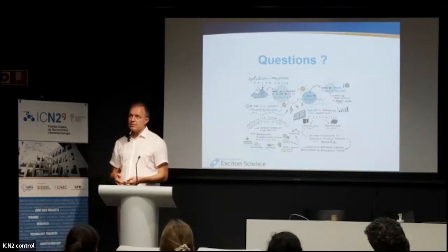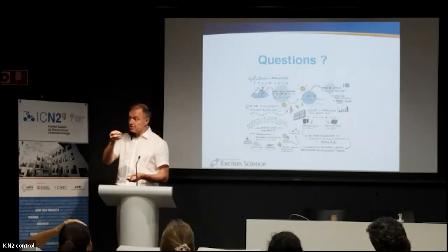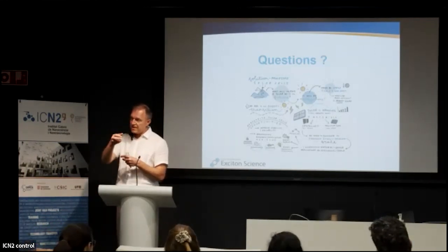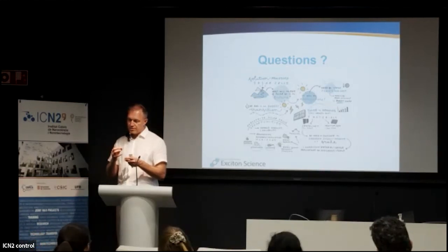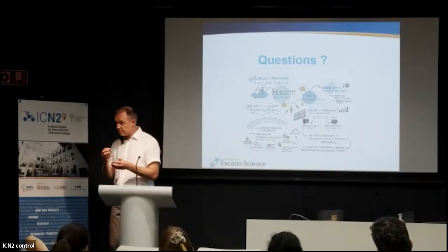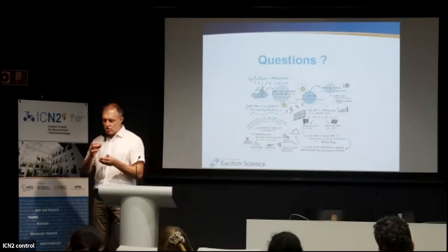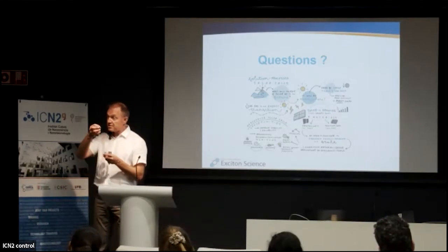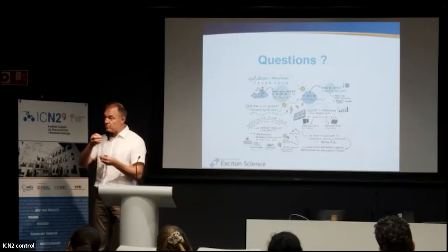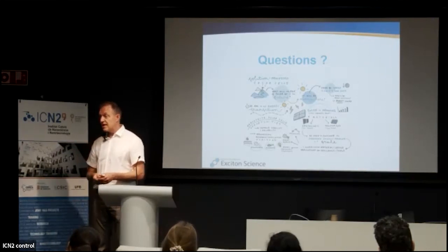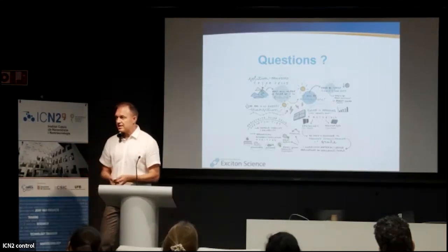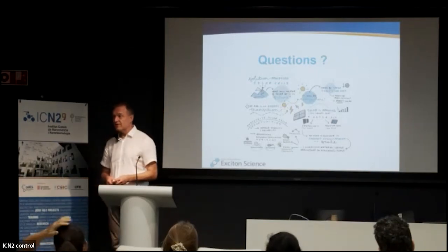That, or you need to think about a mechanism where, for example, the interaction with light causes your halides to jump from where they are into interstitial sites. If in equilibrium at room temperature your halides jump out of their spots and become interstitial, then you have your vacancies, and they can move, and possibly that can be enhanced with light, which I don't know. That's another mechanism that I can think of, but I have no idea which of the two is realistic.